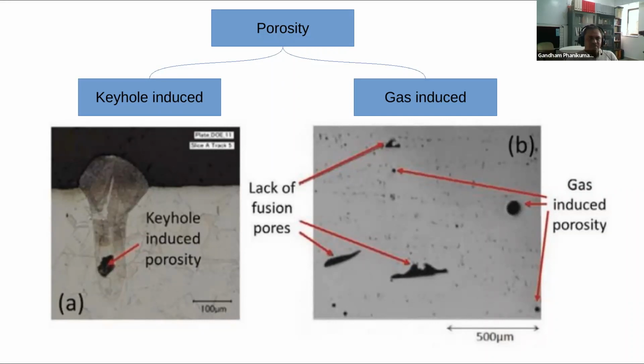Now there is another porosity formation which is quite difficult to remove with respect to your laser characteristics, and that is because of gas induced porosity. That is, you know that the materials which are made using the powder formation, they may actually absorb gaseous substances, like for example, you may have the gas that is dissolved, particularly hydrogen. If it was there, it will be dissolved in the powder. And when you solidify, because a lot of powder surface area is suddenly reduced, then that gas has to be sort of escaping away. And if it doesn't happen to escape, then they will actually coalesce and lead to some gas-induced porosity.